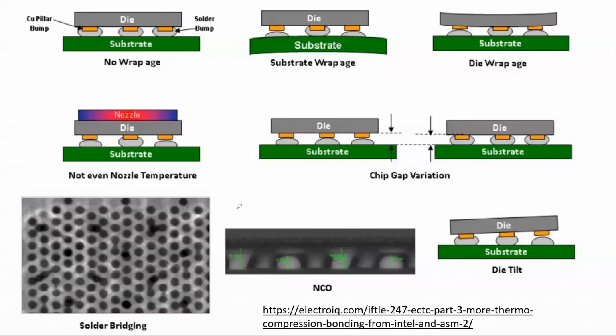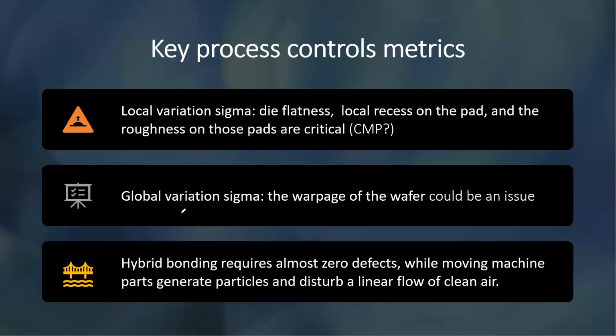And let's look at just this example of substrate warpage, right? It could change. This example is a microbump. It's not hybrid bonding, but just to show you the flavor. If you have substrate bending, either from the top die or from the substrate, you're going to have a problem. Or this die tilt, all these give you problems. And then in some cases you get solder bridging because of that. So that's just to show you a flavor of what I call a global variation sigma.